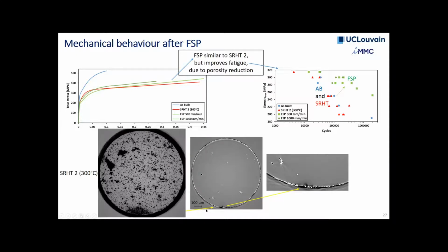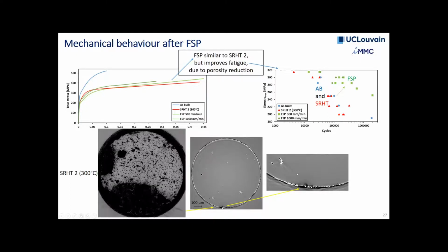Okay, so that was again to show you that after stress relief heat treatment, we have the same situation as what I've shown you in the as-built condition. It's really a subsurface porosity that actually causes the nucleation here. So as-built, stress relief heat treatment, same debate: porosities are causing failure.